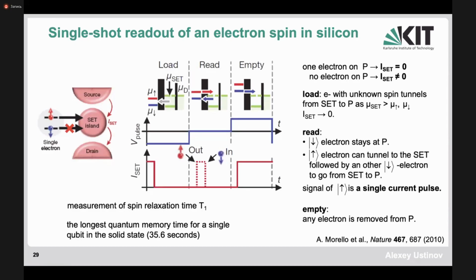Of course, there will be only a state for one electron, but this electron can be either spin up or spin down, depending on the, this is probabilistic. And this electron can come simply by tunneling from the small island into the phosphorus, from the surface into the bulk. And then the two energy states, which are associated with the spin up and spin down state of the electron, which is trapped on the phosphorus ion, are shown here on the left diagram as red and blue line.